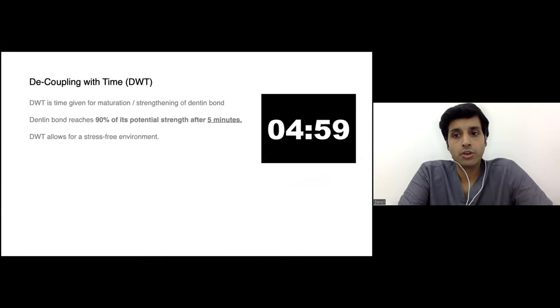Then we go in for the concept called decoupling with time. Decoupling with time is nothing but just wait and watch. We don't do anything in this because, as I said before, the bond to dentine takes time to evolve. That time is shown to be about 5 minutes, and it forms about 90% of its potential bond strength. And 90% of potential bond strength is good enough for us to undertake the future filling procedures. So we place the adhesive, we do a small layer of resin coat, which is 0.5 mm of flowable composite, and after that, once we cure it, we just wait.